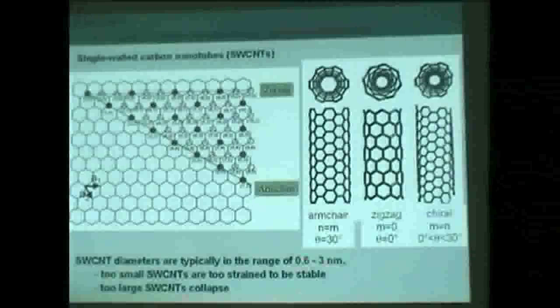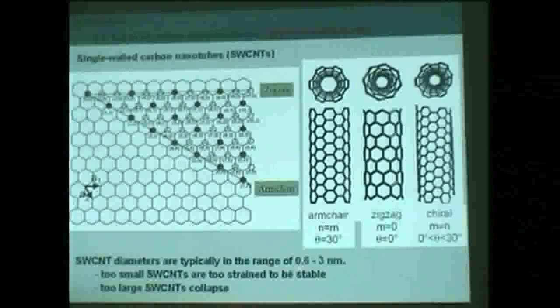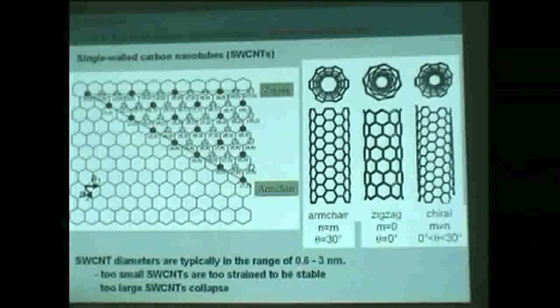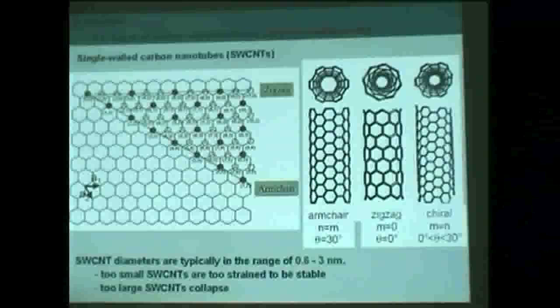What about the maximum value of 3 nanometers? In this case, since this plane is quite flexible, like graphene, if the diameter is too large, the tube can collapse on itself - like a tube that gets smashed. It will just collapse on itself and stick to the other side.